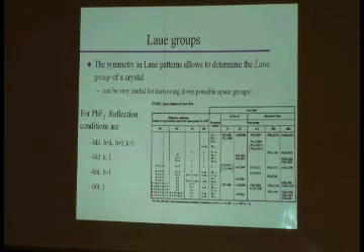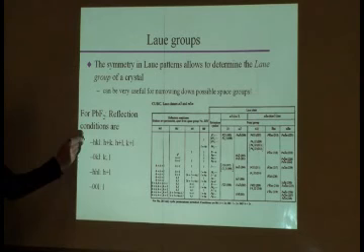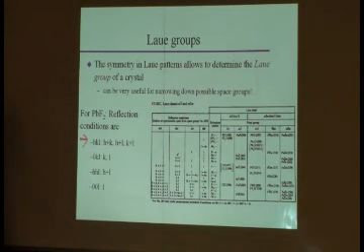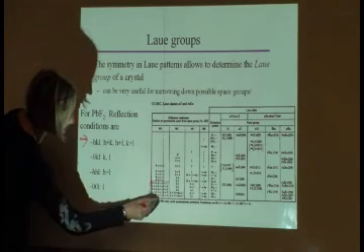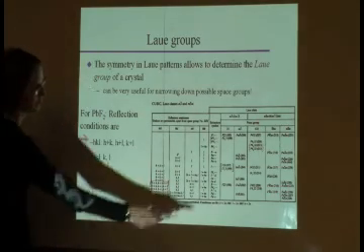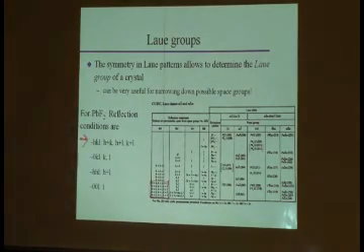In this case, life is pretty easy because things are kind of listed in the order in which you can look at them. First condition, hkl: h plus k, h plus l, k plus l. What does that designate? Face centering, right? If you look at it, that gets us into this part of the table. All of these space groups start with an F. So our first condition already really cuts down where in the table we are.